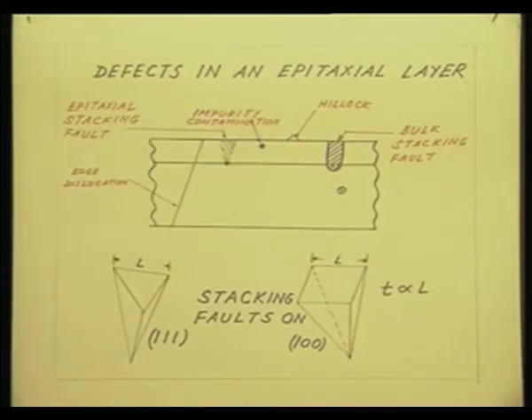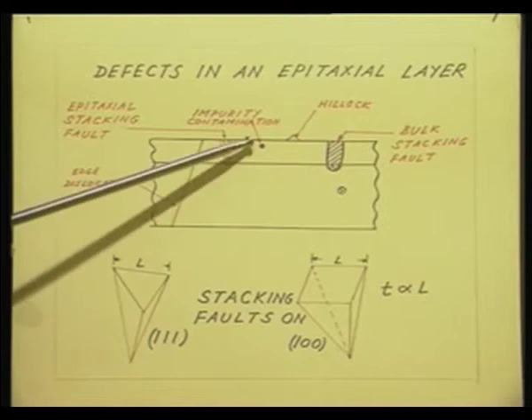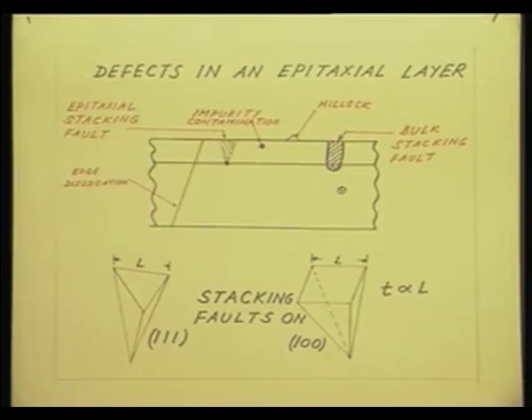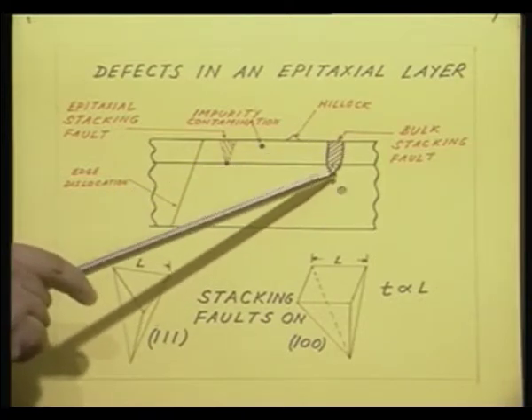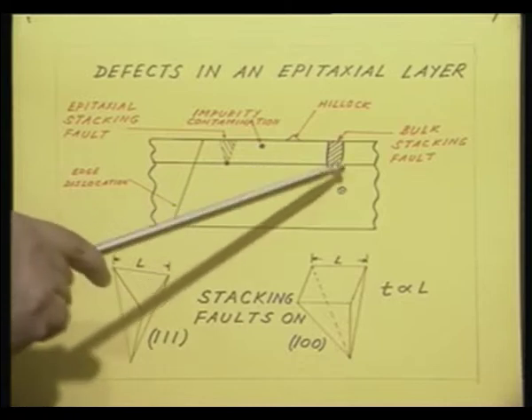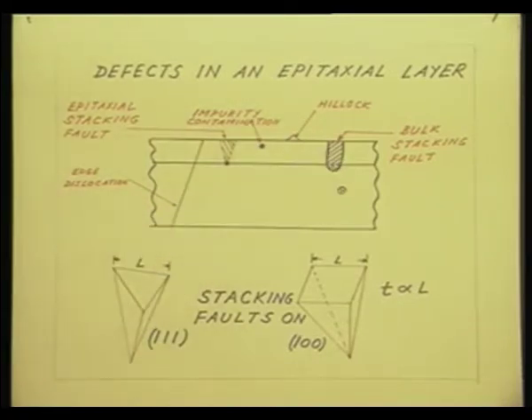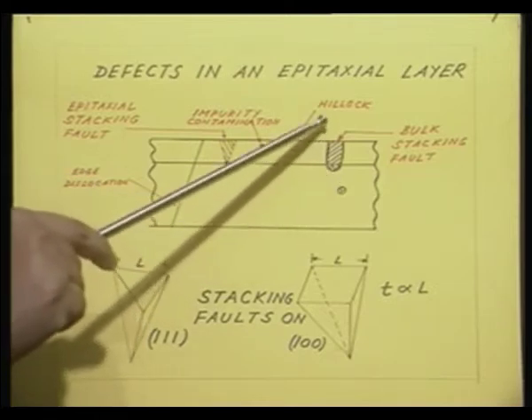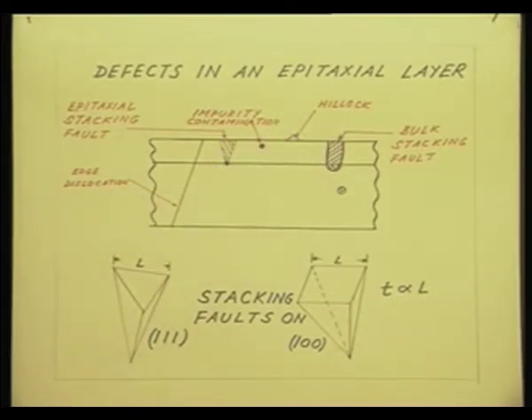The other point is, during the epitaxial growth you may introduce some contamination due to some impurity present in the gas stream or present in the reactor chamber, which is incorporated into the epitaxial layer. The other problem is the growth may not be uniform and you may have hillocks, and if you have hillocks, a dent is also possible. You may have a hillock or a valley present in the epitaxial layer. And finally, if there is a bulk stacking fault which is crossing the epitaxial region, then that will grow into the epitaxial region and form a layer of stacking fault.